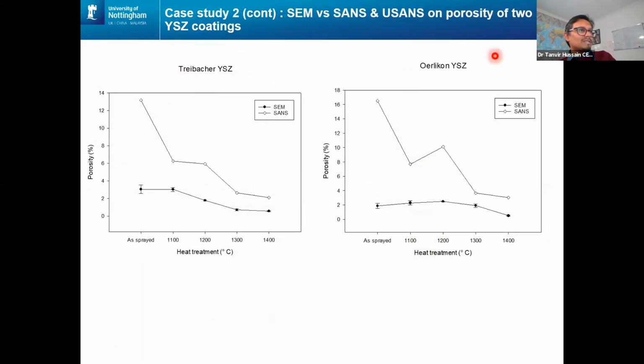These are the two commercial companies that supply suspensions at the moment: Treibacher in Austria and Oerlikon, an international company based in Switzerland. What we're doing is measuring the porosity with different levels of heat treatment using a scanning electron microscope in both cases. We're also measuring the porosity using small angle neutron scattering or ultra small angle neutron scattering, SANS and USANS. We are trying to develop a model here because we all have access to an SEM, but not everyone has access to neutron scattering facilities. So the idea is to develop a model which can correlate the true porosity, measured using advanced techniques, with measurements made on an optical microscope or a scanning electron microscope, so we would be able to predict the true level of porosity.